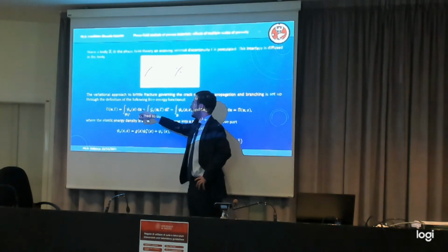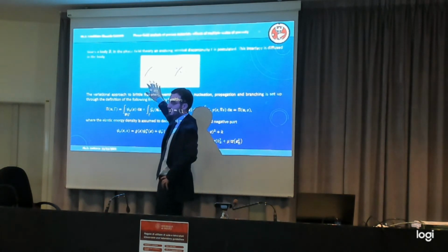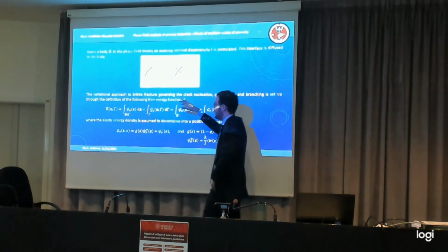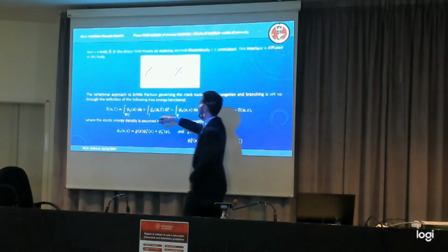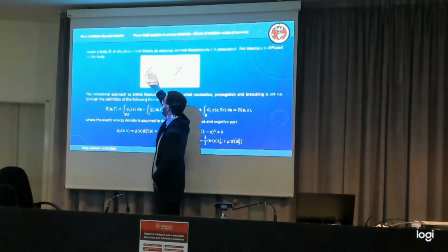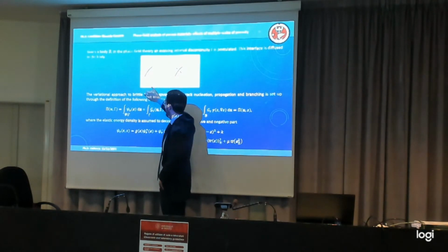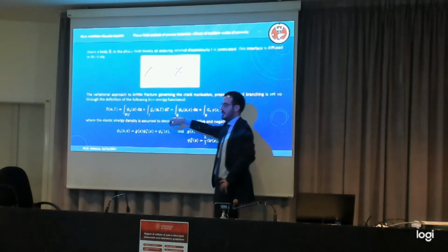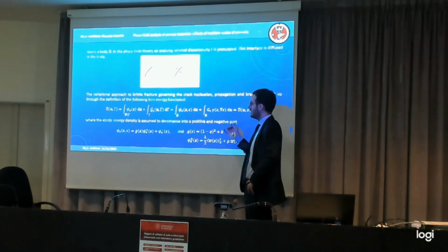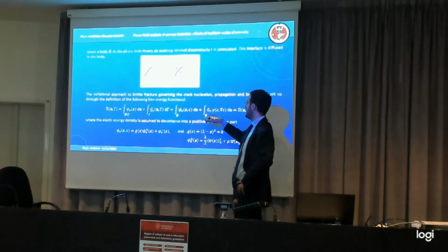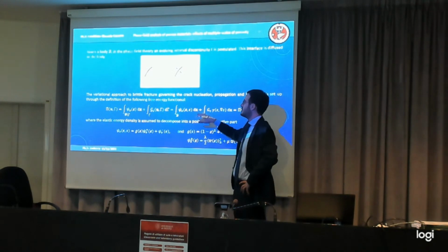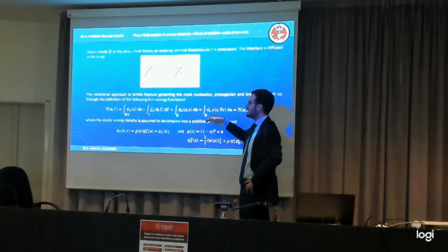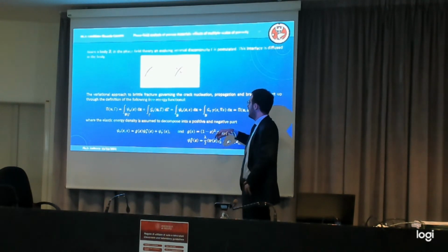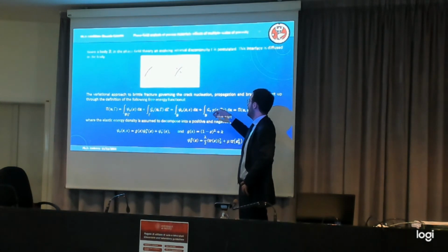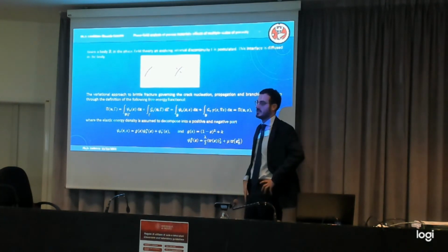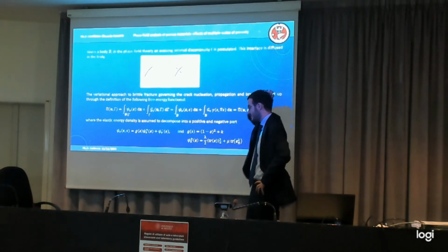So usually, from the variational point of view, if one looks at the Griffith and Francfort-Marigo approach, the surface where the cracks develop is an unknown of the problem and is an extremum of the integration. But by doing this approximation in the topology of the crack, you actually have volume integrals whose limits are not unknown anymore, but you acquire a diffusive field, a scalar field defined all over the body that represents damage.